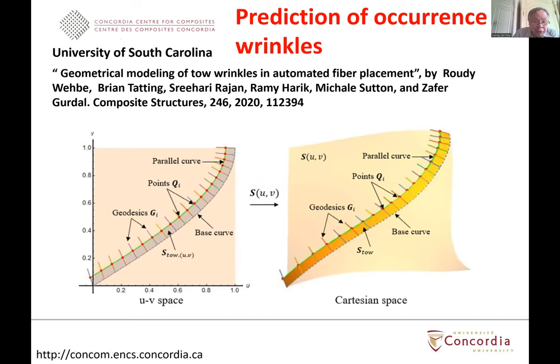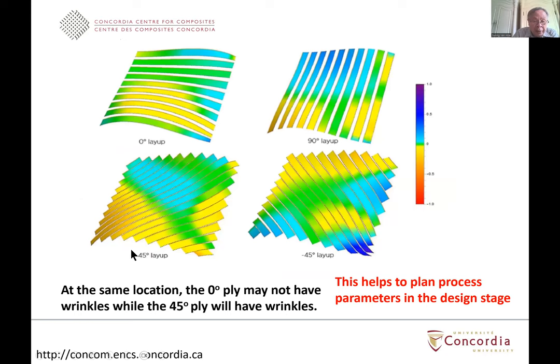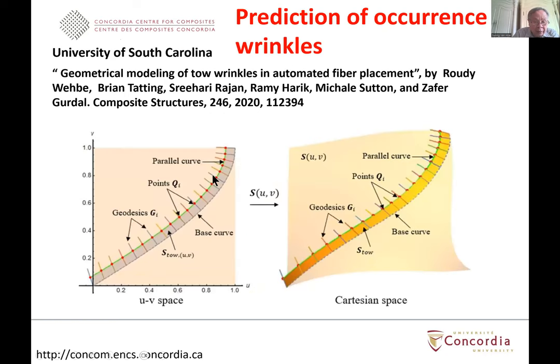Then after that, you are trying to find the other edge. You're trying to find the other edge using the mathematical modeling, in the sense that you follow all of these lines, you follow the geodesic line. That means you follow the equation of the surface along the geodesic. And that way, you can determine the position of the corresponding points for the other edge. So you can find the second edge of the tape, and then from there you can calculate the length of this particular second edge, and you compare the length of the second edge to the length of the first edge. If the length of the second edge is less than the length of the first edge, then wrinkle will appear on the second edge. But if the length of the second edge is longer than the first edge, then wrinkle may appear on the first edge. So basically that is using geometric modeling.